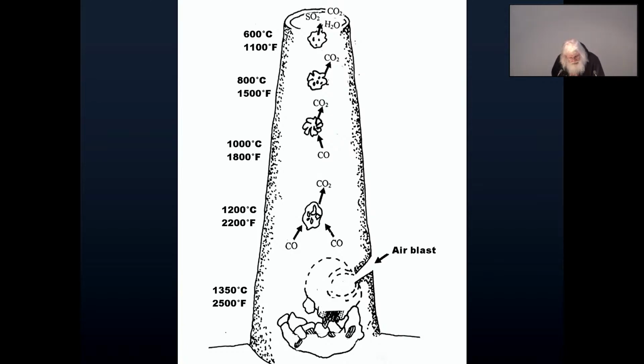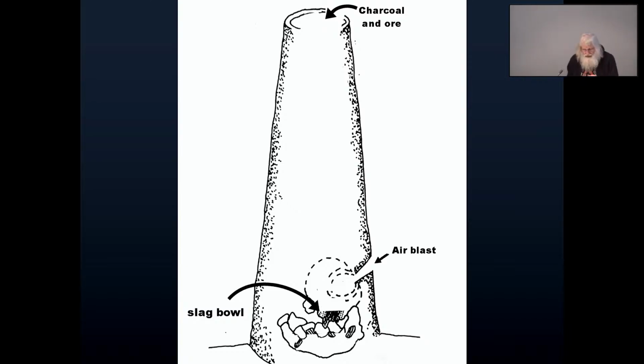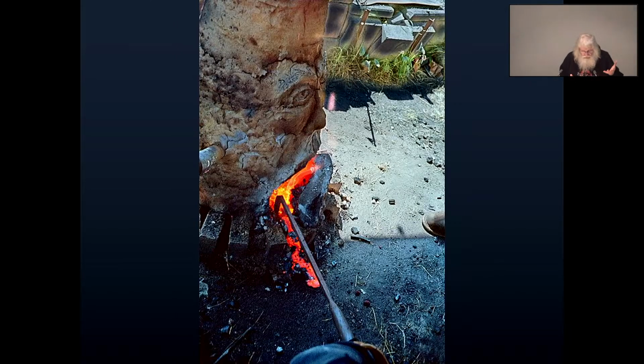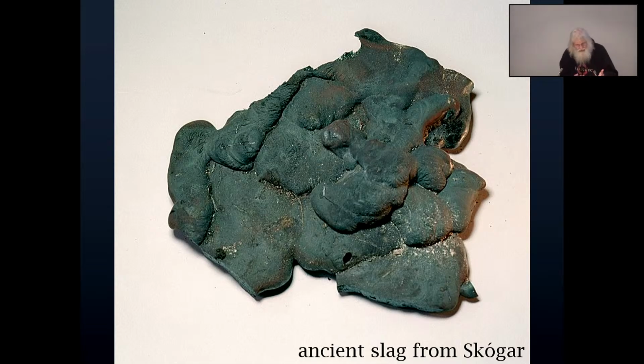And the pure iron drops to the bottom into a liquid bowl of glassy slag. Now, slag is a waste product, but it's necessary for making iron because the liquid slag protects the iron from recombining with the oxygen and turning back to rust. Now, in the actual running of the oven, it's very important to control the level of the slag. Too much and it will drown the process. So the slag is drained off occasionally, and we see that in archaeological finds. We see the hardened slag. It hardens like lava.